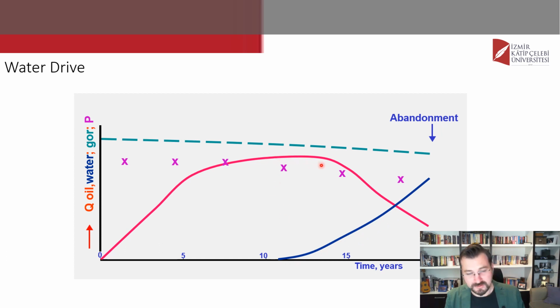Because of that, your oil rate starts to decrease, and your GOR value is decreasing slightly, so your gas phase doesn't have any problem about that. But also your pressure value shows some decrease. Why? Because you are losing your pressure support by time, which is caused by your total production, of course, but mostly from your water production. You start to produce more water, and it shows that your reservoir pressure is going lower by time. So it's certain that you are going toward abandonment.